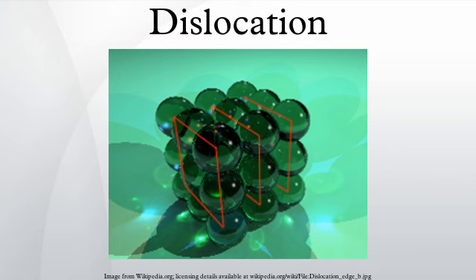Transmission electron microscopy. Transmission electron microscopy can be used to observe dislocations within the microstructure of the material. Thin foils of metallic samples are prepared to render them transparent to the electron beam of the microscope. The electron beam suffers diffraction by the regular crystal lattice planes of the metal atoms and the differing relative angles between the beam and the lattice planes of each grain in the metal's microstructure result in image contrast. The less regular atomic structures of the grain boundaries and in the strain fields around dislocation lines have different diffractive properties than the regular lattice within the grains, and therefore present different contrast effects in the electron micrographs.